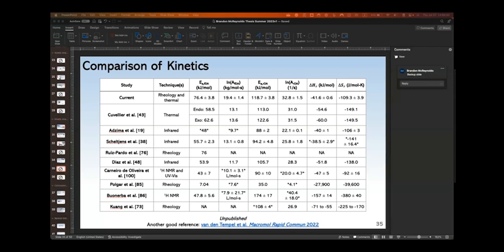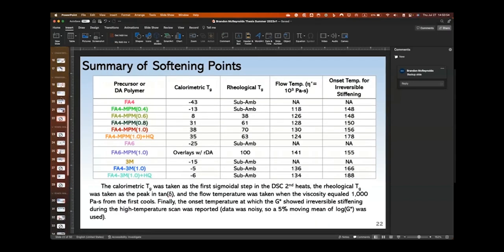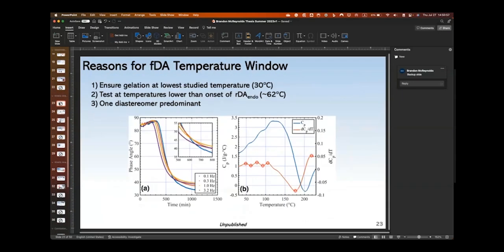Did you use the same thing in your data? I don't think I did. So actually, I did run a kind of multi-waveform test on one of my off-stoichiometric samples. So here, I'll bring it up. I ran a multi-frequency test on one of the off-stoichiometric samples, the FA4-MPM 0.8. And so they roughly intersected at a phase angle of 45. So I took that as, okay, in my case, for my chemistry, tan delta equals 1 is still fine to use.